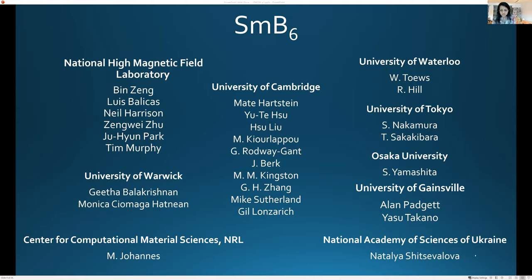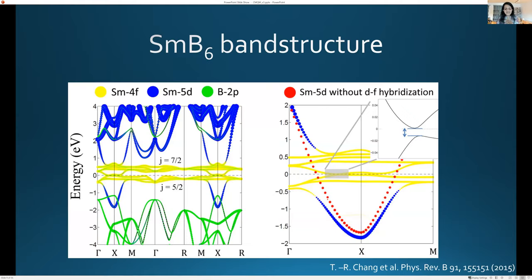Okay, so in the case of samarium hexaboride, just to make contact with the band structures I spoke about earlier, if we look at the right-hand side figure, the red dots are where one would have the conduction band. So as I mentioned, pre-hybridization, if one didn't have hybridization, one would have the red dots and get the conduction band, which the Fermi energy would intersect, and you would get a Fermi surface.